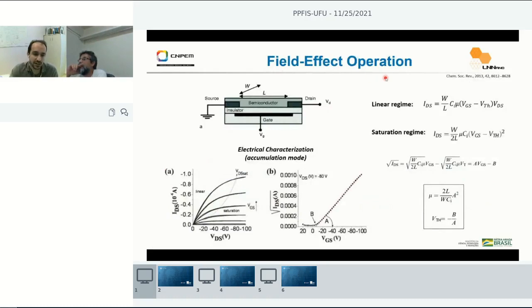To characterize this kind of device, for the field effect transistor operation, you use the same physics as for a solid state device. Here I have a picture of a device with the geometrical parameters like channel length and channel width. The electrical characterization you do is to measure the source and drain current while increasing the source and drain voltage for different gate voltages. You will have a linear regime where the current depends linearly on the source and drain voltage. You also have the saturation regime where the current no longer depends on the drain source voltage, but on the square of the gate voltage.